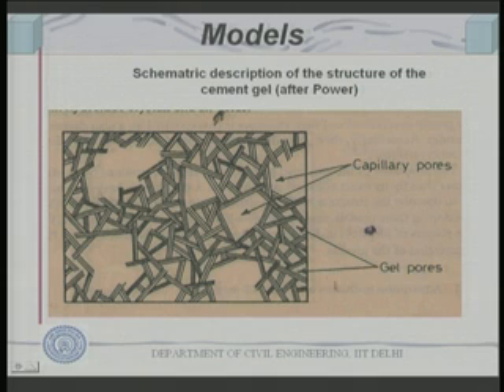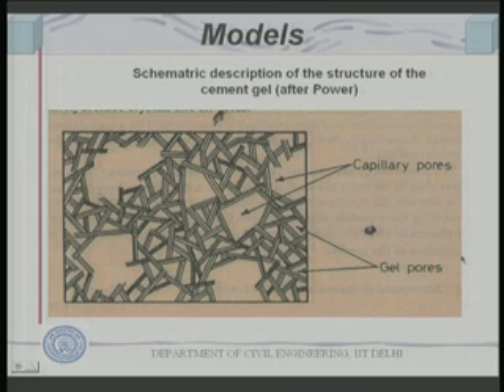Well, Powers gives this kind of a model. He says that there are gels, the layered structure of the gels, those long ones, and the spaces between them are capillary pores, which have been left by water-filled space which has evaporated. Initially you have cement and water, and some of this water-filled space will get occupied by the cement hydrates after the hydration reaction, but some space will remain vacant and the water will evaporate from it, depending upon how much water you have added.